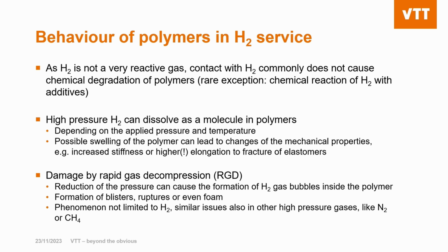Another situation is when high pressure hydrogen has been in contact with a polymer, it has dissolved in the polymer, and then the pressure is reduced. The hydrogen can form gas bubbles in the polymer while it's diffusing out of the polymer. And this can cause blisters, it can cause the rupture of the polymer, or even foam can form. And this is not a phenomenon that is only caused by hydrogen. This also takes place, for instance, in high pressure nitrogen or in high pressure methane. That's also possible.